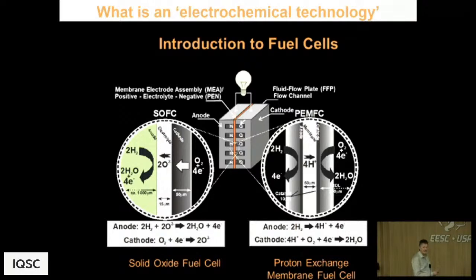It's related to the Gibbs energy of reaction. The Gibbs energy of reaction tells us, in turn, depending on the number of electrons transferred, what the voltage is. So we get a voltage of about 1.1, 1.2 volts if we've got hydrogen and oxygen. And then as we draw current from this reaction, as the reaction proceeds around an external circuit, the voltage will go down. And of course, the voltage will go down because we have voltage losses associated with the flow of current.